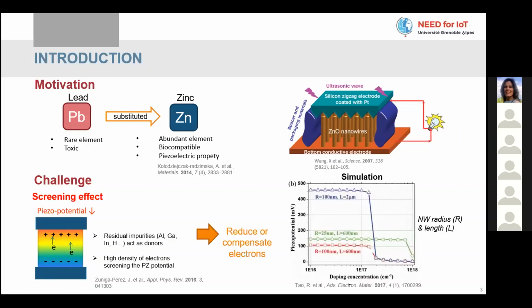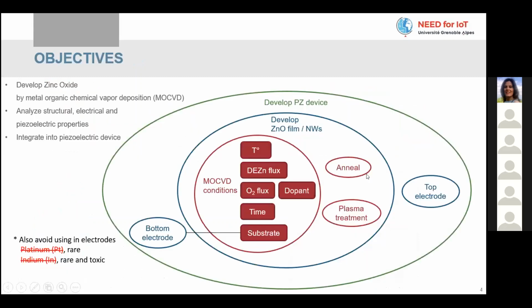And in the other result, we have the simulation. They show that by reducing the free electrons, we can significantly increase the piezo performance. As you can see here, we have the high dopant concentration, and when we compensate the free electrons, we reduce this unintentional doping, and the piezo potential increases in nanowire and in thin film structure.